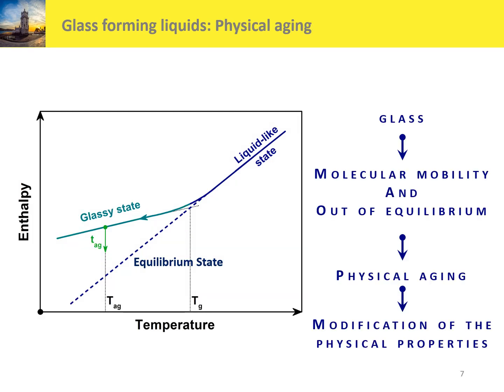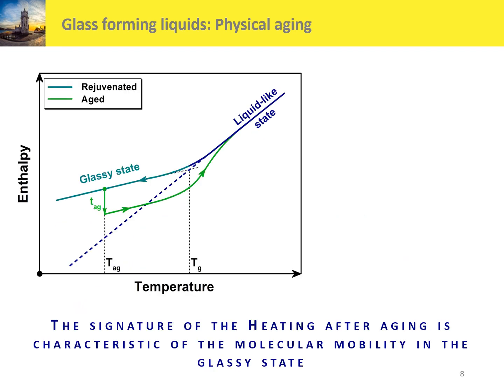Thus, as a glass has a certain molecular mobility and is out of equilibrium, if we maintain the glass at a temperature below the glass transition temperature, it will try to lose its excess of enthalpy to reach the equilibrium state. This natural phenomenon is called the physical aging, and this physical aging modifies the physical properties of a glass. And it is important to specify that the signature of the heating after the aging is characteristic of the molecular mobility in the glassy state.